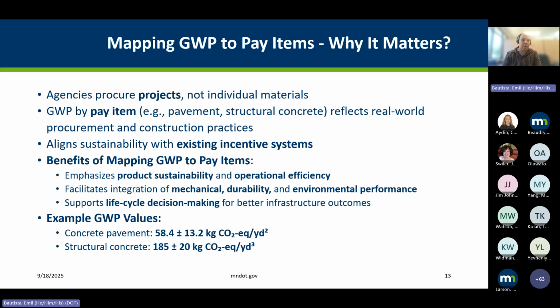You can see for concrete pavement, we have around 58.4 plus or minus 13.2 kilograms of CO2 equivalent per square yard. This is concrete pavement placement. And then you can see that structural concrete is significantly higher, but that's because it's by cubic yard. So these are two different units. This should not be compared, the same way that we shouldn't be comparing EPDs for concrete of two different specifications or strength levels.